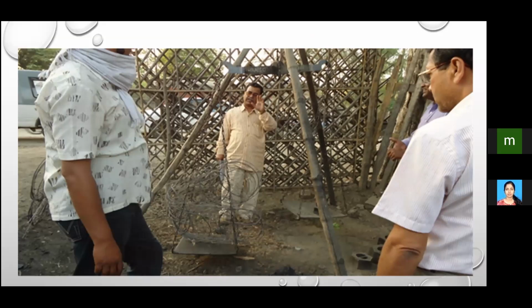So we checked whether the sewer diameter was maintained, or whether inferior quality sewer pipes were used, in terms of the reinforcement requirement. So we physically verified, as you see here. We took the weight of that in a nearby workshop, and we saw the percentage of that compared to the total pipe weight, and whether the stipulated percentage was okay or not. So we checked that here.